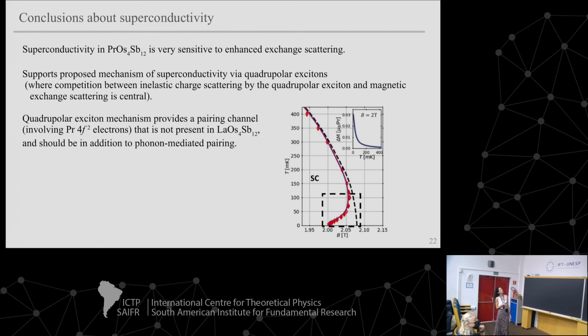Okay, so just to summarize for the superconductivity, hyperfine interaction enhances exchange scattering in the superconducting phase. And the superconductivity is very sensitive; it's a very small effect. This is a tiny magnetization, but it's noticeably suppressing the superconductivity here. This supports the proposed mechanism of exciton-mediated superconductivity. And this would be a pairing channel on top of the electron-phonon-mediated pairing that we also see in the lanthanum compound, we think.